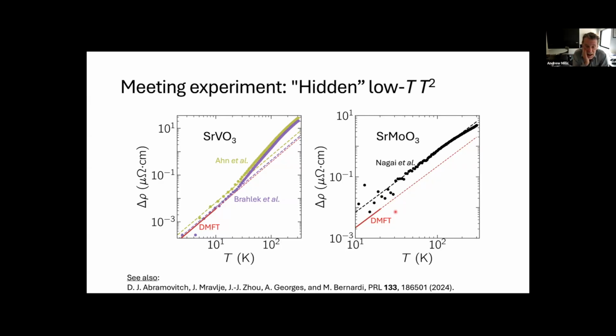The reason that I'm asking is that if I look at strontium vanadate, the adjacent one, the high temperature resistivity, which comes from phonons, has a different slope, whereas the strontium molybdate seems to have the right slope, just an offset. So is it your view that there's some problem with the coefficient of T squared, or do you think something else is going on? I think from this data, it's just impossible to tell.